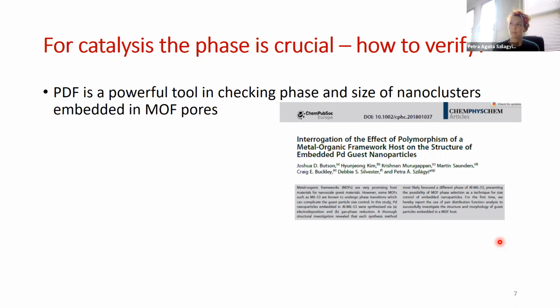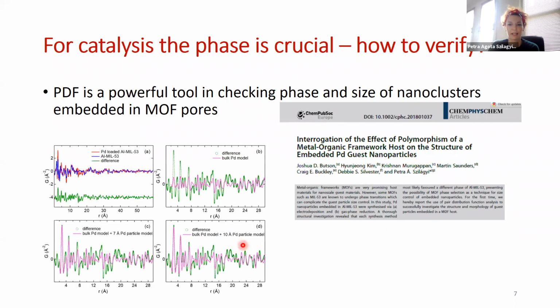So we are very interested in exploring the atomistic structure of these clusters because, of course, that determines many of their properties. And we had developed this tool, the use of pair distribution function, to determine what the atomistic structure of these clusters is. In this case, we added palladium in MIL-53, an aluminum-based framework. What we assumed is the following: if we collect total scattering data on the empty framework and subtract it from the total scattering data of the palladium-laden framework, the difference curve should be basically a representation of the guest material in itself.